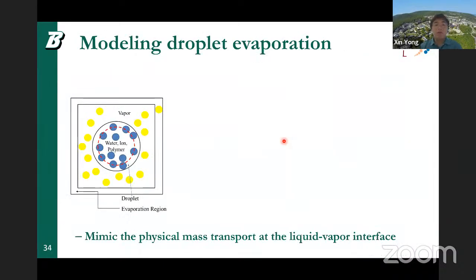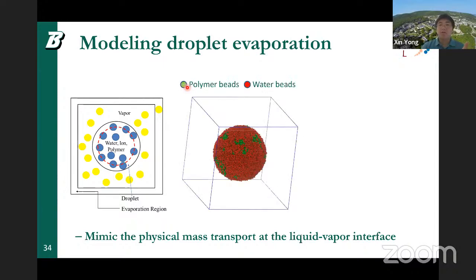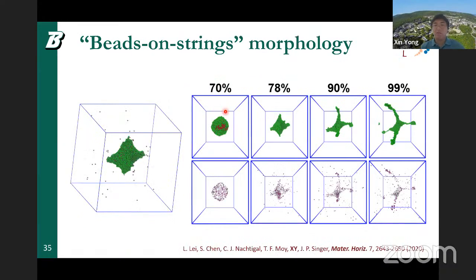Now to model evaporation, we do it phenomenologically. Here we have vapor beads representing, essentially we're doing a two-phase flow. We have vapor beads outside, and then the internal is a droplet with ions and polymers. And so we evaporate, or we basically remove the water beads only near the surface of the droplet. But then to maintain the constant density of the DPD requirement, we'll add back solvent beads to the exterior region. And so this will allow us to mimic the physical droplet evaporation subject to the D2 law.